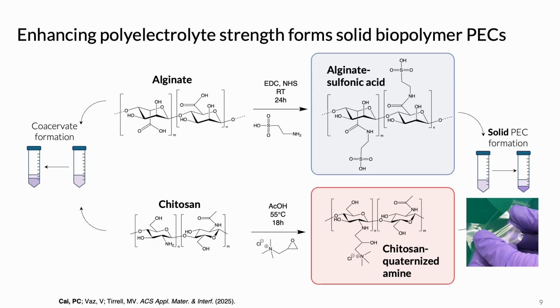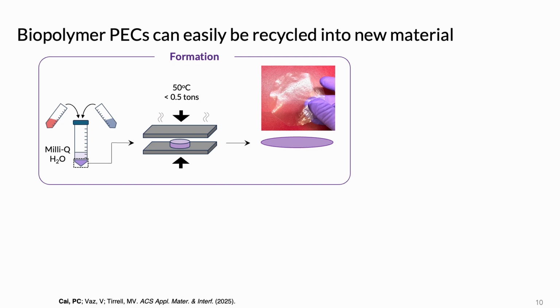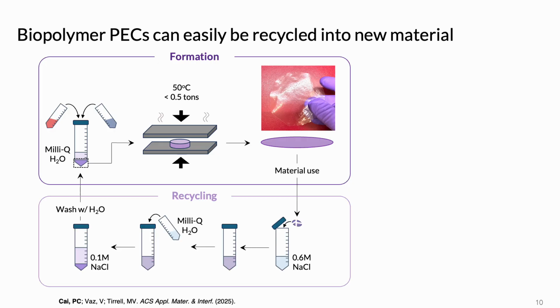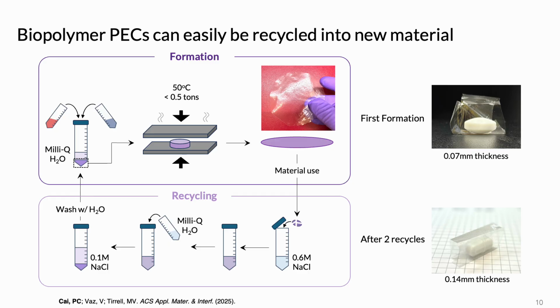It looks very plastic-like. I formed these films by taking the solid out of solution, pressing it into a film between two heated metal plates, and letting it dry. After use of the film, the material is fully recyclable by placing the material into salt water, where it will fully dissolve into the liquid, and then pure water is added to dilute the solid concentration and drive solid-liquid phase separation once again. The bottom solid phase is then repressible into a new piece of plastic. Here you see the picture of what the material initially looks like after first formation and also after 2 recycles, and the white stir bars are around the size of candy, so one could imagine a potential application might be single-use candy wrappers.